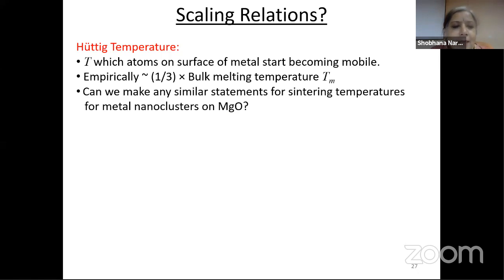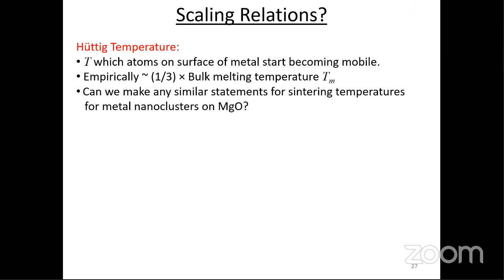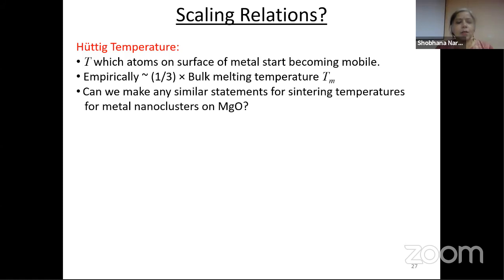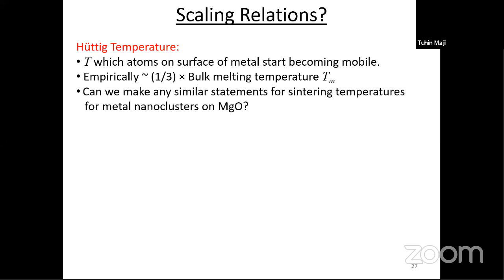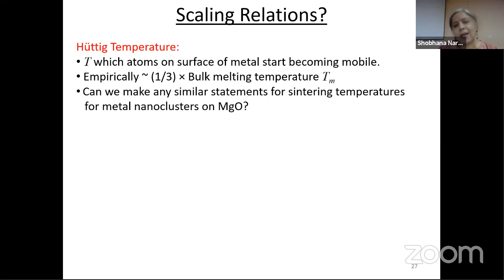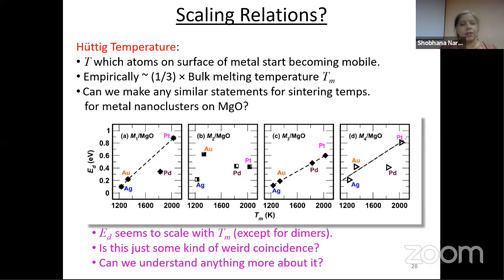So to look for scaling relations in these diffusion barriers, the first thing we were inspired by is something called the Huttig temperature, which is if you have a metal surface. So this is not a cluster of a metal on an oxide substrate, just a metal surface. Empirically, it's known that if you reach roughly 1/3 of the bulk melting temperature for that particular metal, that is when the atoms on the surface of the metal start becoming mobile. So we wanted to see if there's any similar statement for the sintering temperatures for metal nanoclusters on MgO.